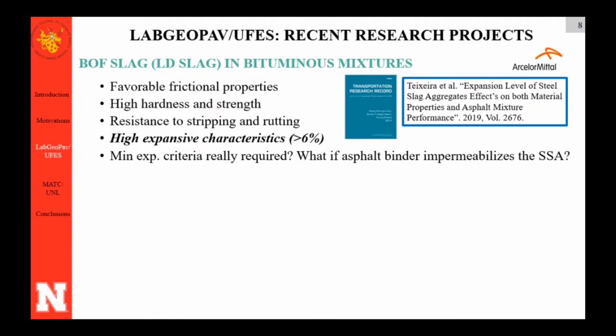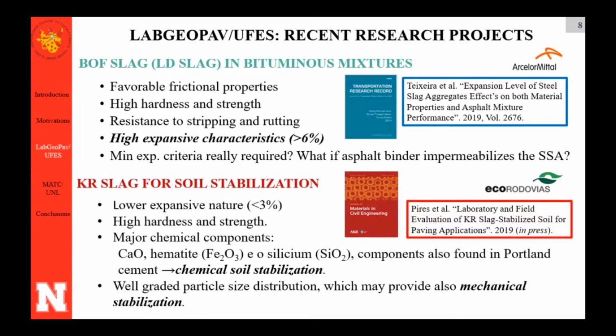So this study was published this year on the TRB. I can say that it is in the initial part, still a lot to be investigated, but we published the results, and I'm going to show you in the next few slides the results we got. Another study that we also have about the use of slag is the use of KR slags, another type of slag that does not have expansion at all. Actually, there is, but it's much less than LD.